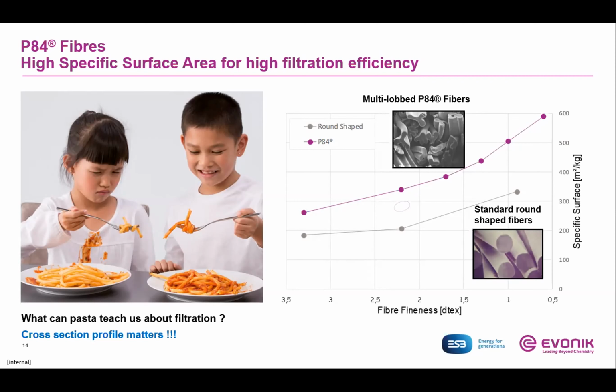If we go down even further this line, as I mentioned before, the finer the fiber, the higher the surface is, we can end up at specific surface areas of almost 600 square meters per kilogram of fiber. Calculated back on the standard fabric weight of a bag, that is something like 300 square meters per square meter of filter bag, provided just by the fibers. So this is the top end.